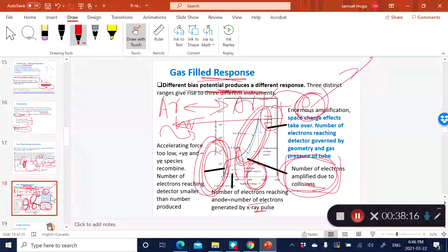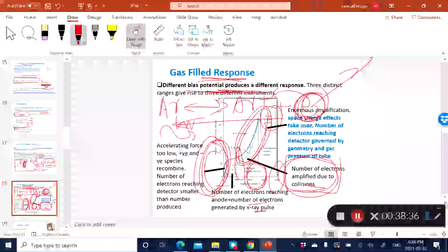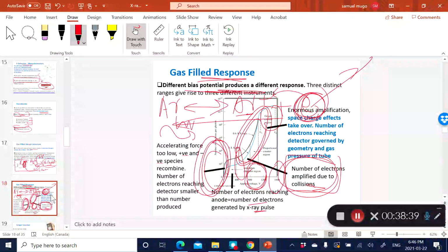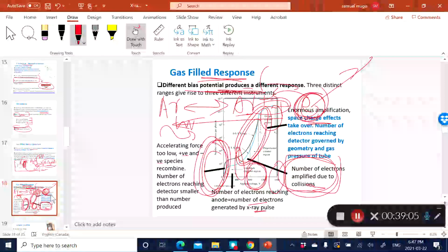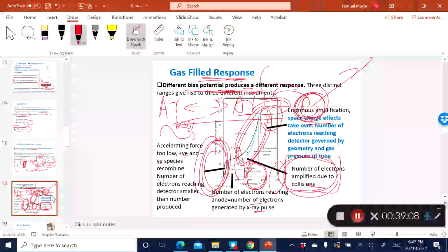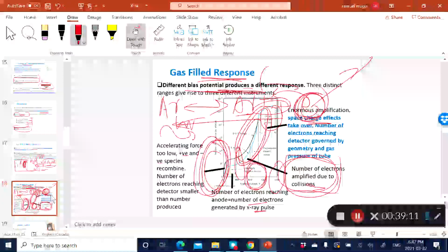And finally, you've got this other region here where the voltage is very, very high, meaning you're very quickly pulling away these electrons, and it's a very energetic beam of electrons because you're using very high positive voltage to pull it away. And as you pull it away, it's colliding with so many of the other argon gases, generating even much more cations. And because of that, the relationship is actually not linear because of what you refer to as a space charge effect. You start getting a repulsive effect because you've got a lot of ions constrained within a very small area within this tube, and so you get repulsive interaction, the so-called space charge effect. They take over, and so the relationship is actually not linear, in terms of the number of electrons per photon being generated.